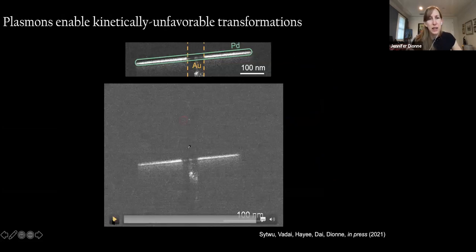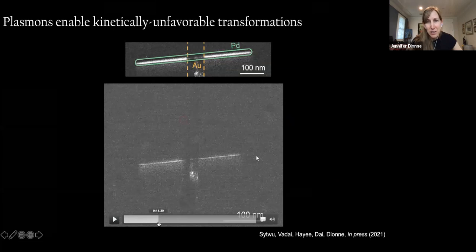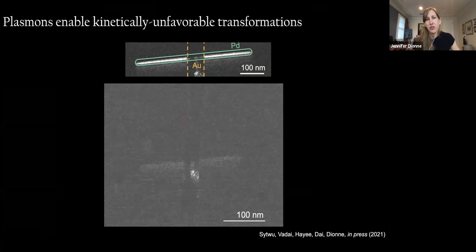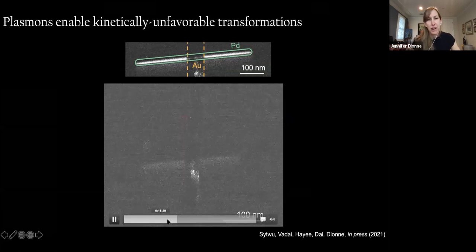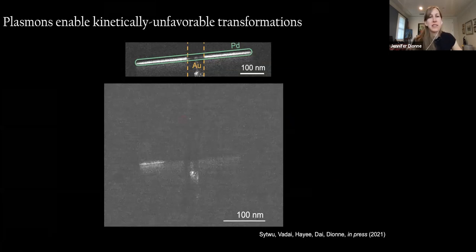So here's just one image, and recall that in the dark, we only had loading and unloading from the tips. But what you'll see, and I think it starts right here around the 14th second, is that upon illumination, we can actually get hydrogenation and dehydrogenation from the center of the bar. So I'll play that again just so you can watch the dehydrogenation, in this case occurring from the center of the bar and then moving across one side and then over to the other.